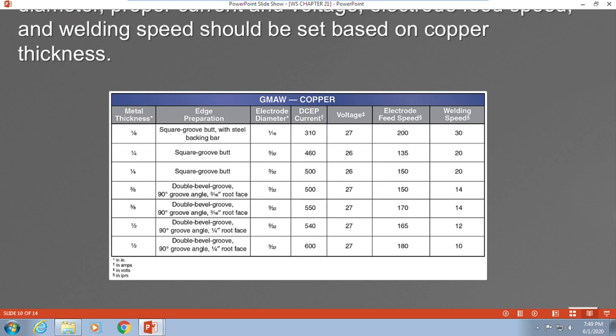but we really need to pay attention to how much heat we're actually having to put into this. Copper dissipates heat very, very quickly. So at an 1/8 inch, 1/16 inch diameter, our current is 310. Our volts at 27 and our feed speed at 200. Anything over, let's say 3/8 of an inch needs to be preheated to a minimum of 400 degrees because otherwise it will dissipate the heat so quickly you couldn't get it to stay.